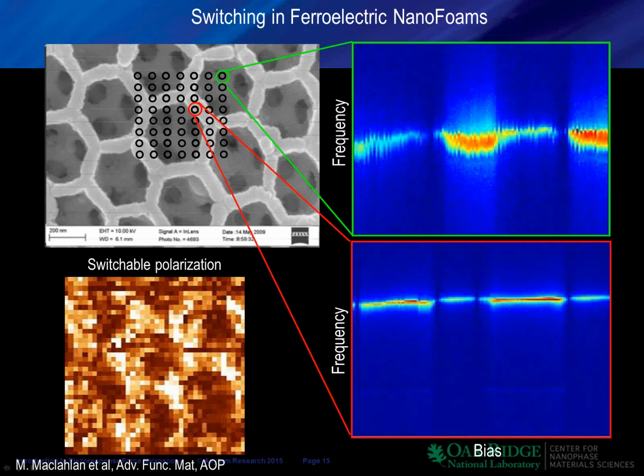However, both for solid space and for the empty space, we can essentially measure the switching behavior, and we can map it in a two-dimensional map. So you can clearly see this switchable polarization map that shows this hexagonal motif. So the first advantage of the addition of band excitation to switching spectroscopy PFM is that it works on very rough surfaces.